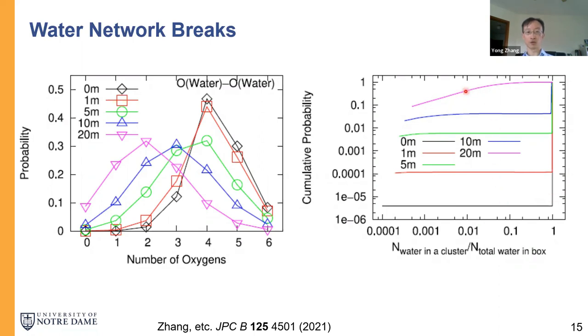At high concentration, we see a slow increase of small water clusters. But basically, most of the water exists in some size of cluster. They don't connect to each other anymore. So we just mentioned TFSI going from isolated molecules to a big network with increasing salt concentration, and here it is the opposite, from a network to small clusters.